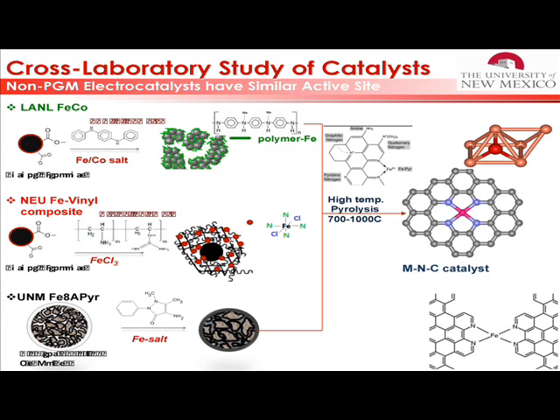It is also extremely important from a structural point of view, because the microstructure, the one in the Dodelet/Jaouen concept, practically does not contribute to the electrochemically accessible surface area. And if your catalyst is to be active in a real fuel cell, it will be very active in a rotating disk electrode because liquid water will get into it. But if you have a triphase interface, this catalyst will suffer from diffusion limitation in the gas phase immediately.